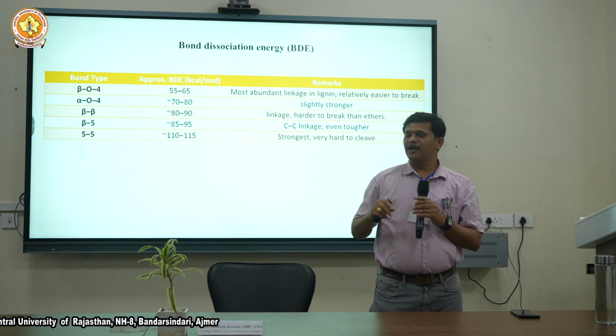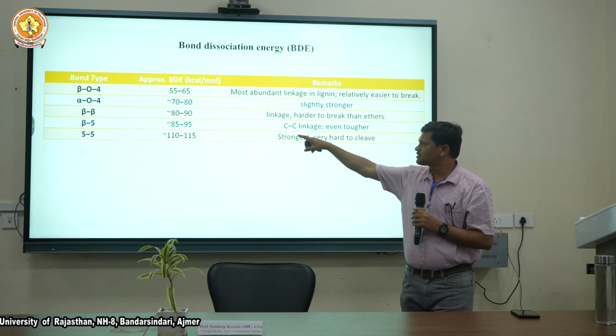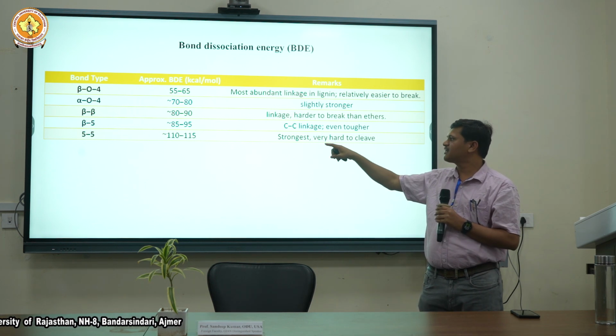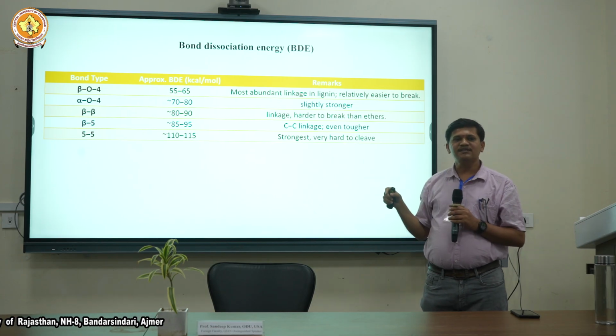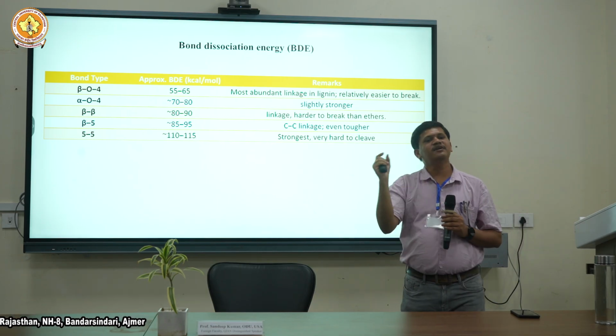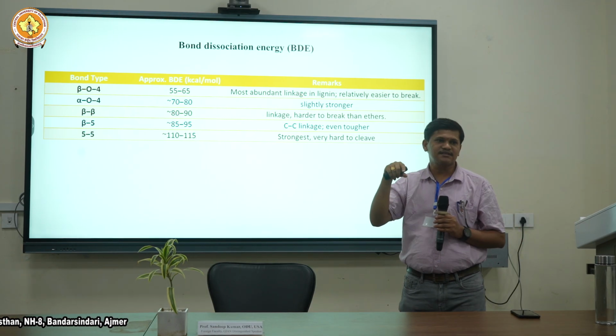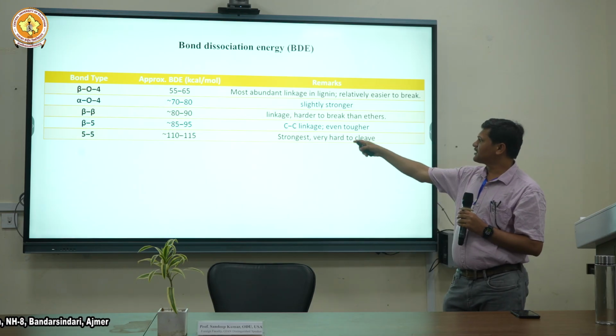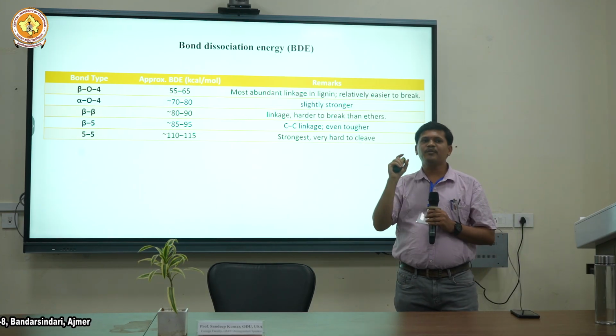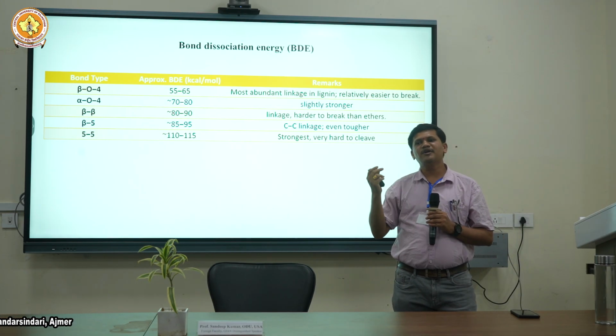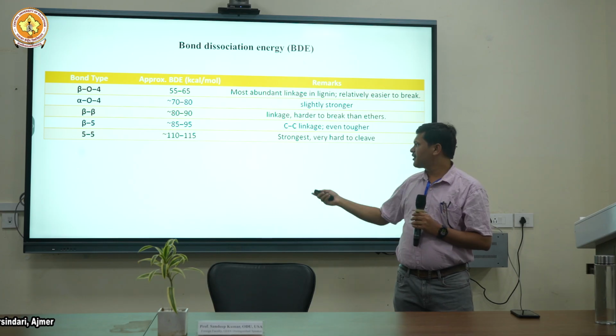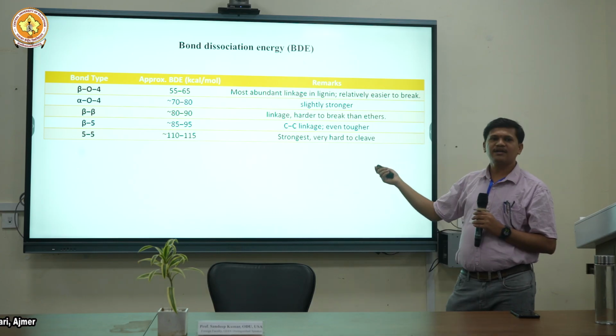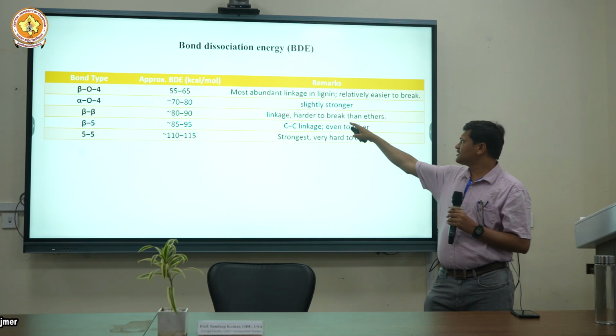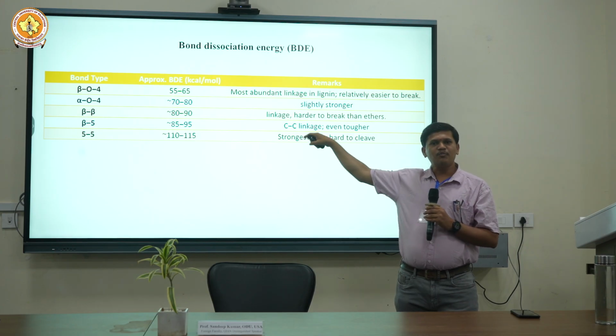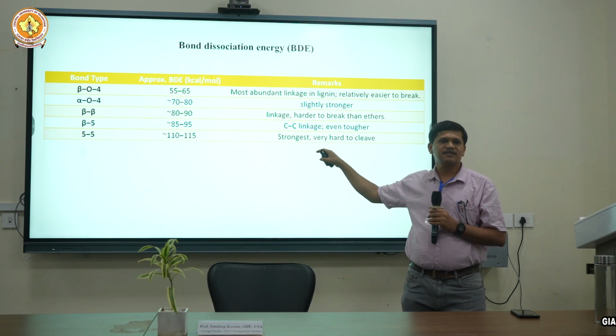And this lignin is a polymer. It does not have only beta O4 linkages, it also contains alpha O4, beta beta, and beta 5 linkages. This 5 represents the carbon 5 and carbon 5 of the different aromatic rings. So under such conditions, with increasing carbon content, the breakage is becoming more hectic, and breakage of the 5 linkage is very hard. And this is in case of different components, two catalytic components we are discussing.